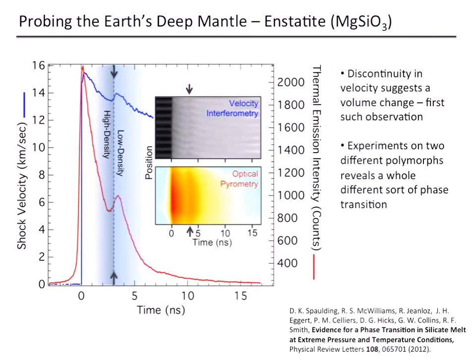So another material that we looked at again was Enstatite, or MgSiO3, which you can think of as just a mixture of MgO and SiO2. We see similar, but even in this case more pronounced structure in the thermal emission in our decaying shock wave - we see this big bump. But for the first time, we also saw a simultaneous discontinuity in shock velocity, which you can see here in the raw data where the arrows are. This discontinuity in velocity suggests that there's a volume change going on in the material.